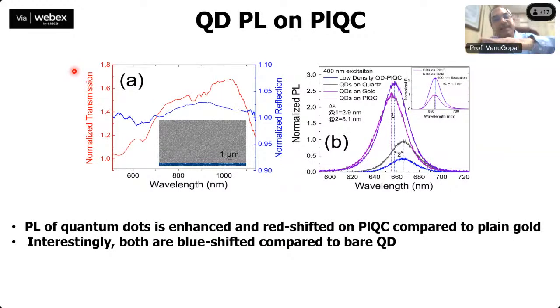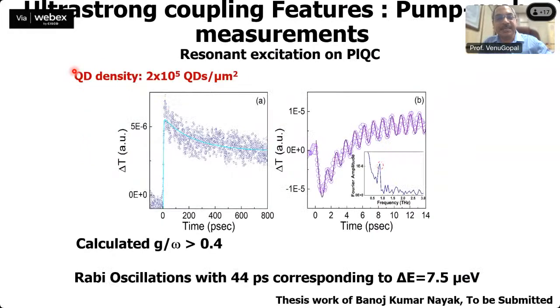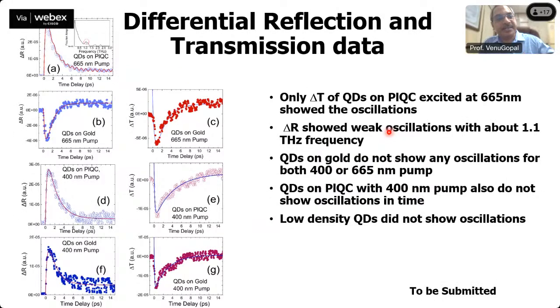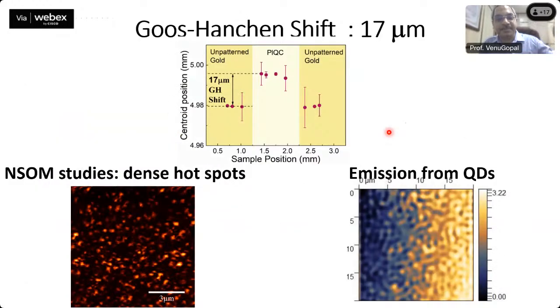And we looked at density-dependent quantum dot photoluminescence from these structures. We showed basically that there are these oscillations which are happening at short time scales, but these timescales are much longer than the plasmon lifetime. So when the plasmons are no longer expected, we still see these oscillations, and these are density dependent. Only at very high densities we see these. At low densities or non-resonant excitation, we do not see these oscillations. And we measured the Goos-Hänchen shift, the plasmon propagation length, and measured the emission coming out up to the propagation length of the plasmons.